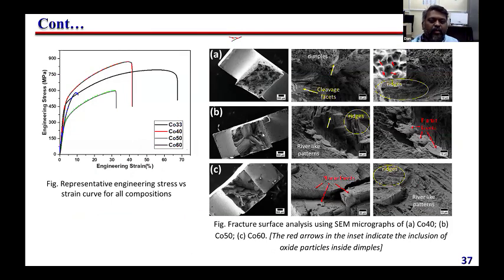So here, when you increase this proportion, usually the strength is enhanced, but at the same time the ductility goes down. Basically the 33% composition is giving better ductility with better strength. If you take 40%, the strength is really good as compared to equiatomic, but the ductility went down to 40%. Also 50 and 60, if you take, can't obtain very high strength, with very little ductility; the samples broke. All the samples broke mainly because of this transformation. The martensitic transformation is basically dominating.